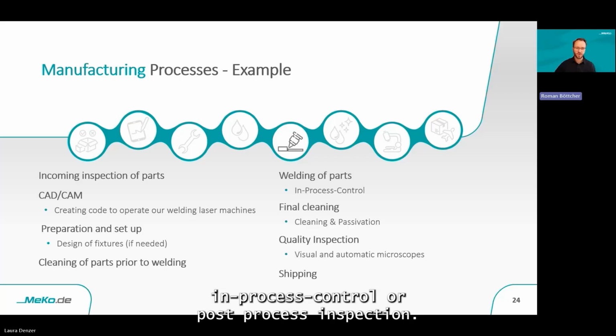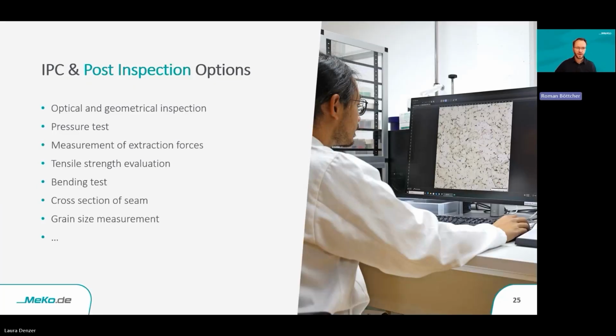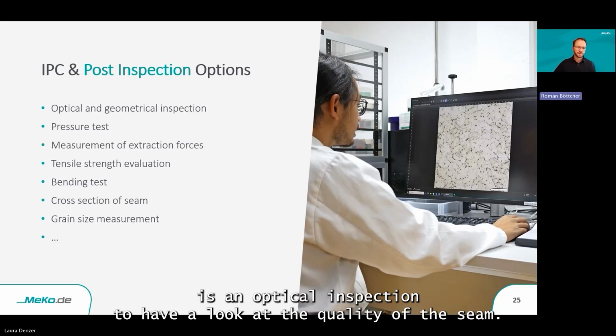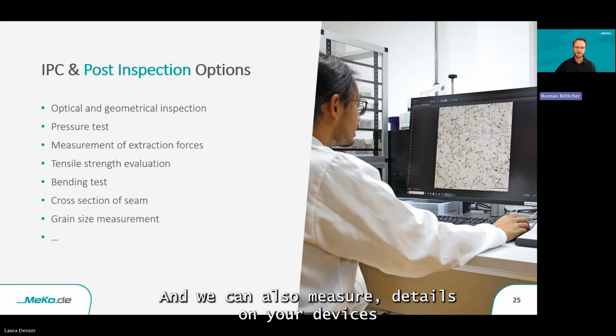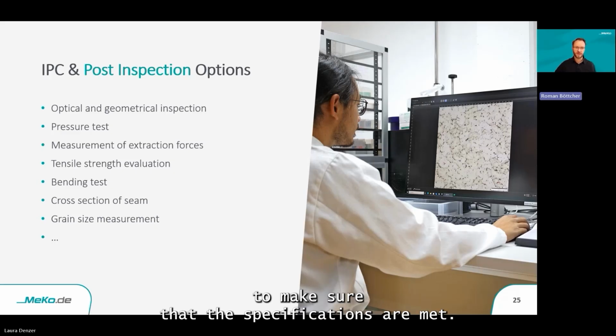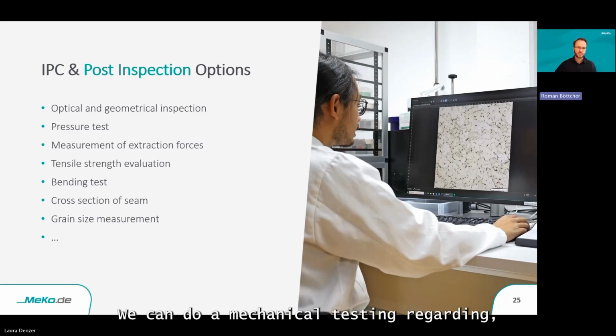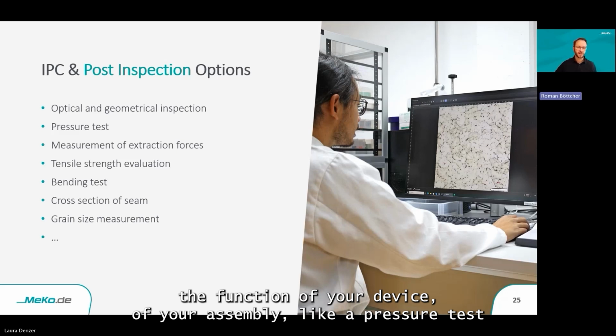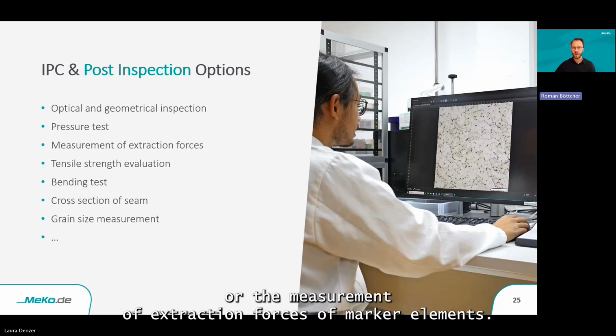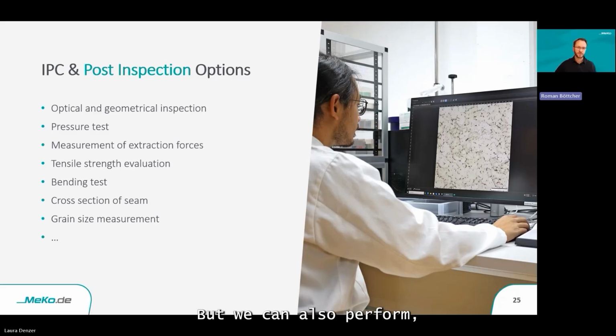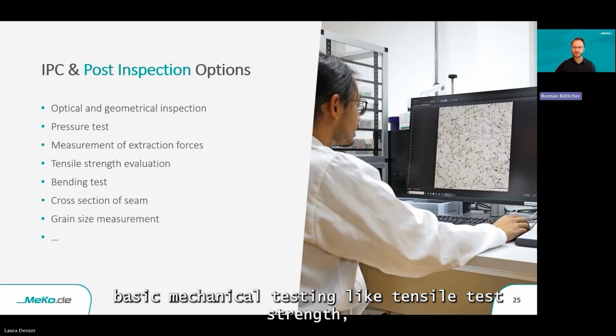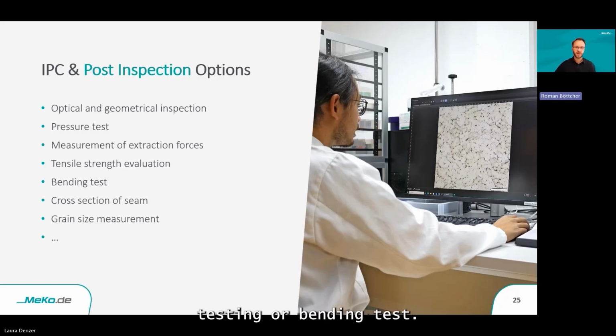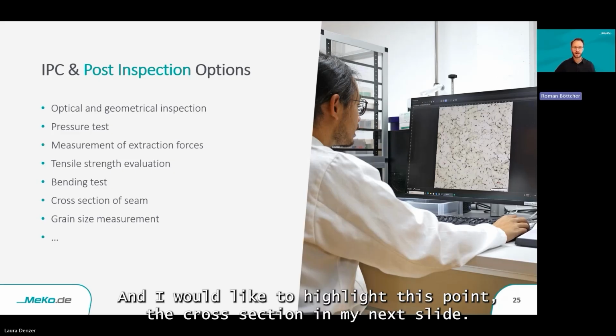That's the in-process control or post-process inspection. What we use there is an optical inspection to have a look at the quality of the seam, and we can also measure details on your devices to make sure that the specifications are met. We can do mechanical testing regarding the function of your device, of your assembly, like a pressure test or the measurement of extraction forces of marker elements. But we can also perform basic mechanical testing like tensile test, strength testing or bending test. And we can also do cross-sections of the seams to perform a grain size measurement. And I would like to highlight this point, the cross-section, in my next slide.